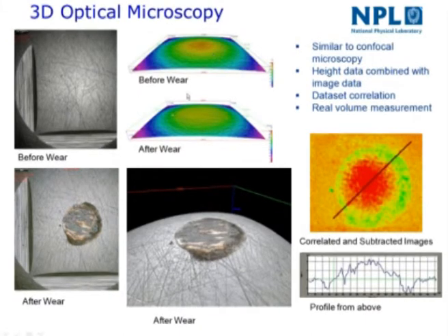This is a height map before wear has taken place. You can get a height map after wear has taken place, and you can then subtract these two images. You can do something called image correlation, data set correlation I've called it there, and you can subtract the two, and the result in this case is this micrograph here, where the red is the true wear volume, which you can determine pretty accurately with this instrument that we've used here with a precision of about 10 nanometers. I should say precision, not accuracy, actually. And that's the red, and the green is actually the built-up material around the edge. So this is higher than the original surface, and this is lower than the original surface. And you can see that in a profile that's taken on that line there. So this is the wear, and this is the built-up area on the surface. So we can, using this sort of technique, get very accurate measurements of wear, and that's becoming increasingly useful.